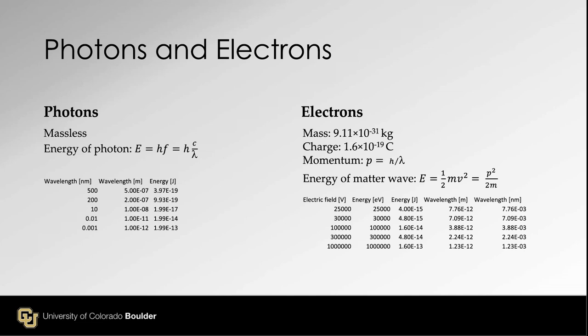So typical electrons in an SEM environment, a tungsten filament SEM, which is the very standard instrument, at 30 kV, that electron has a wavelength smaller than a nanometer, okay? And the energy is much higher there. A big e-beam writer typically uses 100 kV as the incident electron. The wavelength is really small. But my point here is that even a regular, conventional SEM can have those electrons. Electrons do have much shorter wavelength compared with photons. This is one reason why we can achieve much higher resolution using electrons.